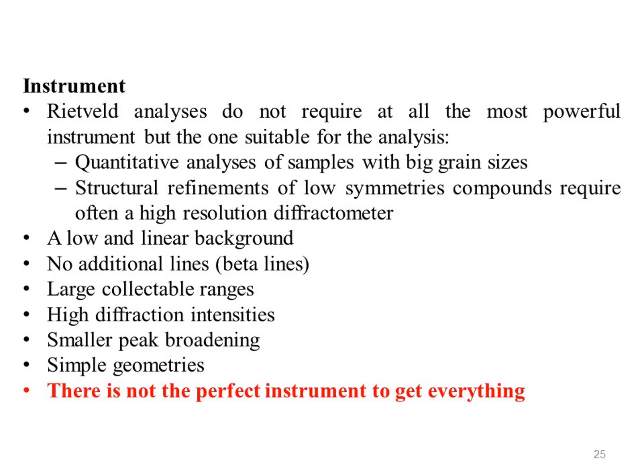A low and linear background is the first requirement. Non-additional lines, no beta lines, are also in general preferred. Large collectible ranges are important. High diffraction intensities should be achieved. Smaller peak broadening helps the analysis, reducing overlaps. Simple geometries are better for subsequent Rietveld fitting. There is not the perfect instrument to get everything.